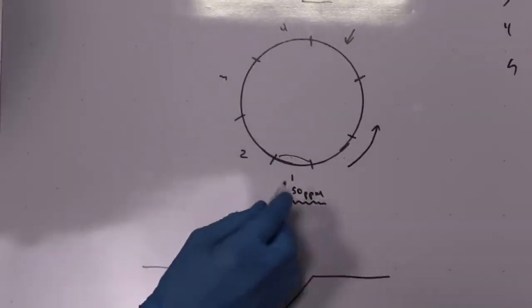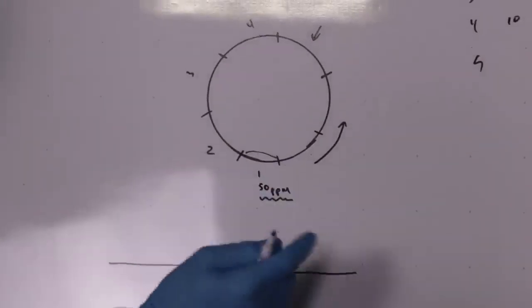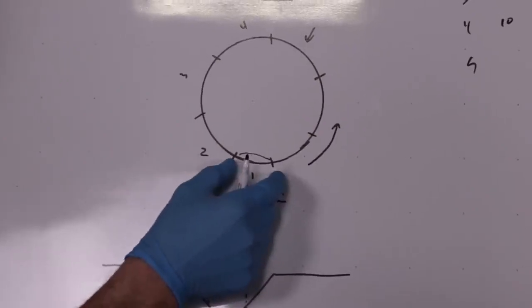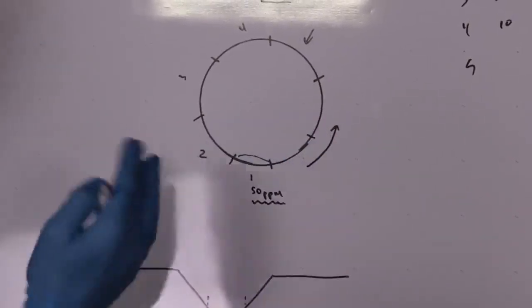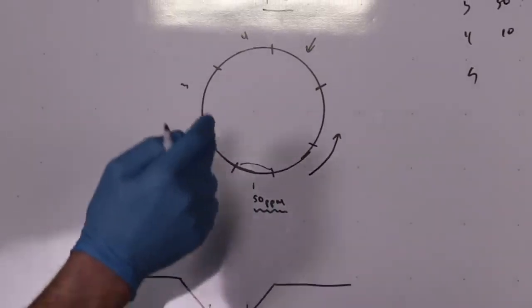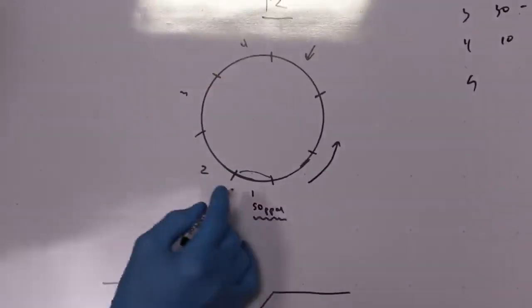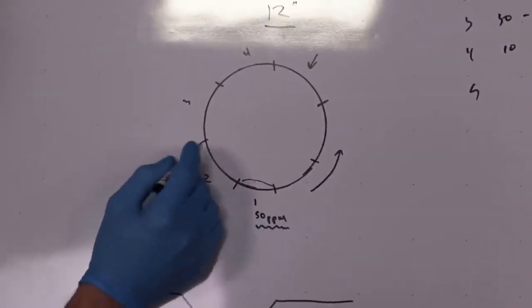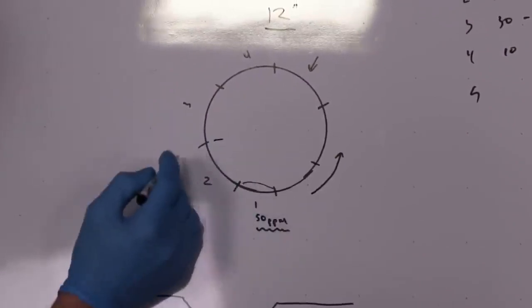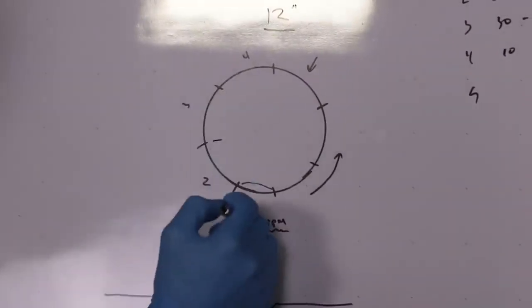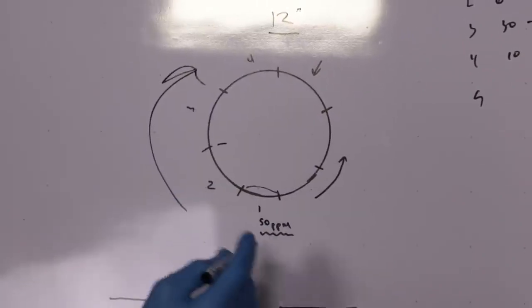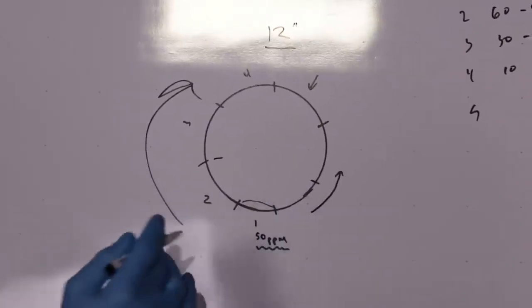But basically you're going to get, say, 50 parts per million or less or more, so you're going to weld a small section there, and you're just keeping everything taped up and keeping the argon enclosed inside the pipe. Once you do the bottom there, then you can open a little bit more tape up here. You can weld that section. Essentially, as you close more and more of the root pass, the parts per million of oxygen, the atmosphere inside the pipe, is going to get better and better.